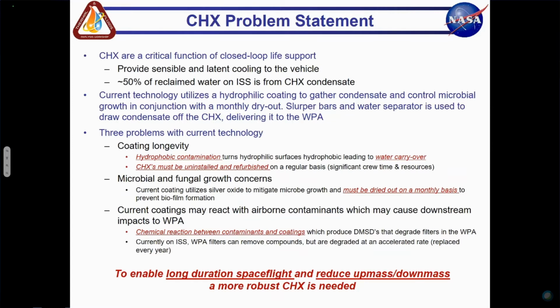The current technology that we use to control the sensible and latent cooling uses a hydrophilic coating to gather condensate and control microbial growth, also in conjunction with a monthly dry out. As that water condenses, it wicks out onto the surface because of the coating, and then there are slurper bars embedded into the heat exchanger that suck that water out in conjunction with an active water separator.